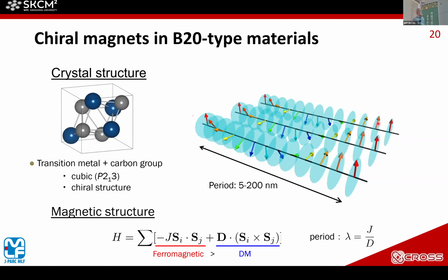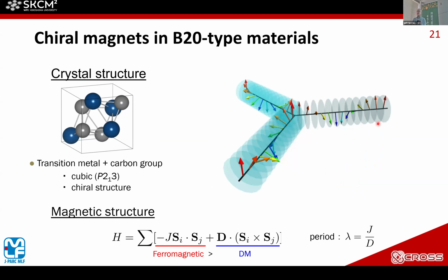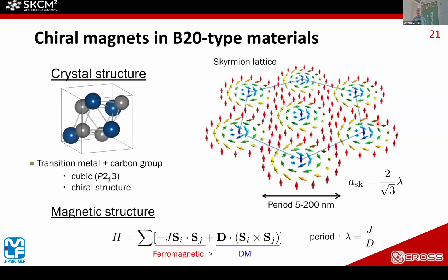And its period is about 5 to 200 nanometers, which is incommensurate with the lattice parameter. And also, nowadays, in this case, the propagation vector is just one direction. But when it takes a multiple-q structure like this, then the skyrmion lattice appears, which is a kind of particle. So magnetic particles form the structures.